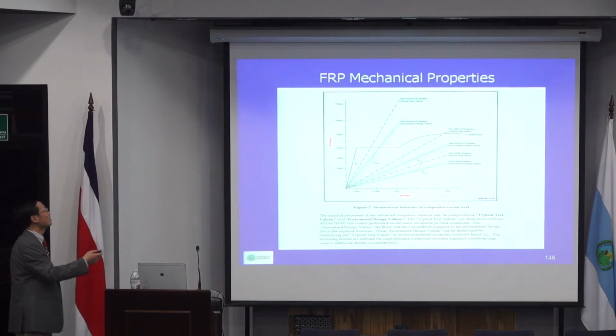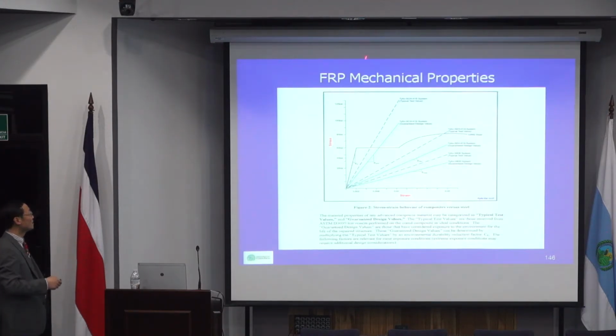The material property of FRP is very similar to steel, but the difference is, I actually have a comparison. Steel typically has linear elasticity, and after yield, it has a very large plastic zone. After the plastic zone, it may actually enhance a little bit, but in general, we assume elastic and plastic. But FRP material is almost like glass. It's just elastic only until it breaks. In other words, it does not give you any warning before it fails. That's why whenever you use FRP material, you don't use it at its ultimate capacity. You only use it at certain levels.